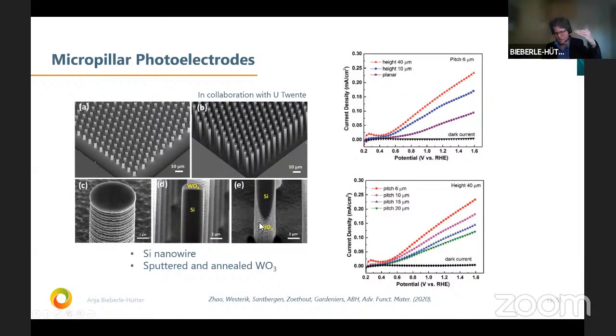But you see that really down to the bottom of the micro pillar, we were able to deposit tungsten. We find tungsten oxide actually. And on the right side here, you see that we changed now the height of these pillars and the pitch, so the distance between the pillars. And you see, as we have higher pillars, we get better performance, higher current densities.